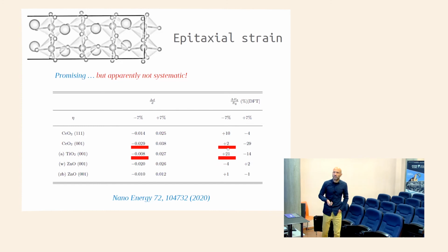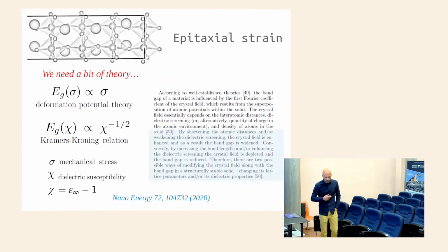So there seems to be some piece missing here, right? And this is what we try to find out. What are we missing, right? As I said before, we didn't say anything new, but we just looked into the literature, and we found out that, of course, there is not only one way to change the energy bandgap, which is given by this deformation potential theory, which is mainly based on stress, or if you want, on a strain, which I've called delta D divided by D, so how the distances between atoms change.